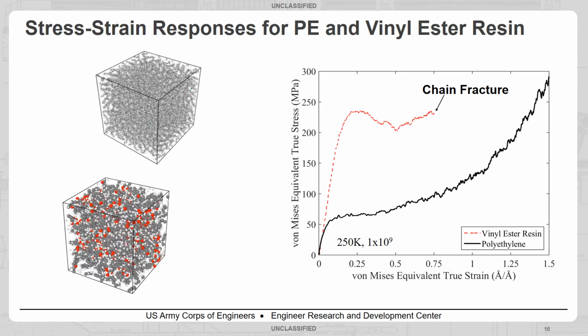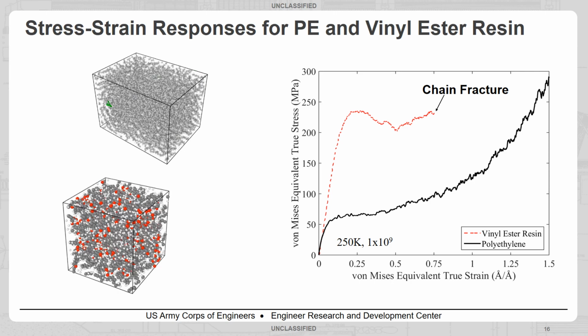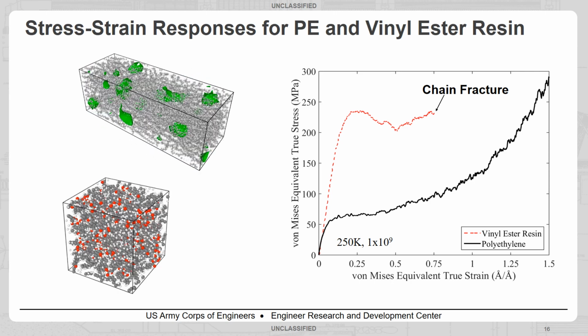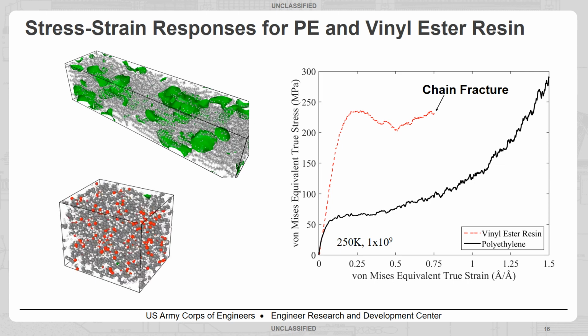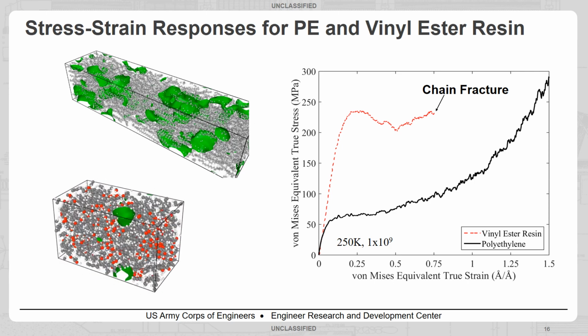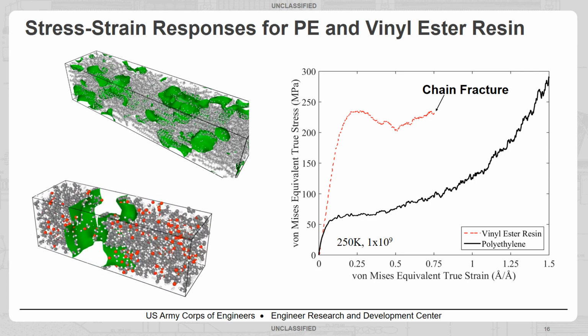So here we have the stress-strain response for our polyethylene and vinyl ester resin. Polyethylene deformed first, and we see a well-distributed damage within the system. And then we have deformation here of our vinyl ester resin. We see voids start to nucleate in a localized region, eventually leading to this catastrophic failure, which is what we see here in the stress-strain response. You have a much more brittle-like failure of our vinyl ester resin, at only about 0.75 strain.